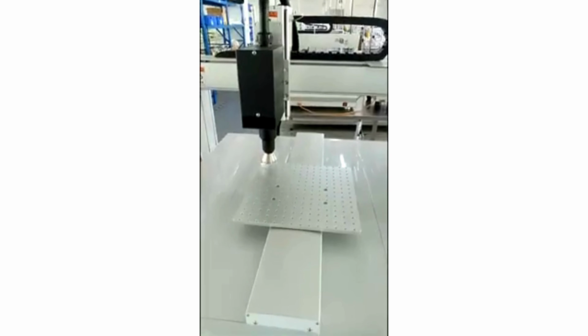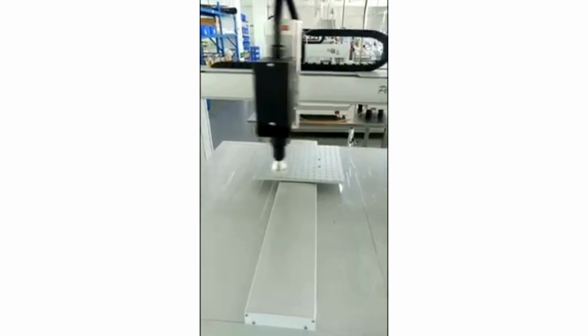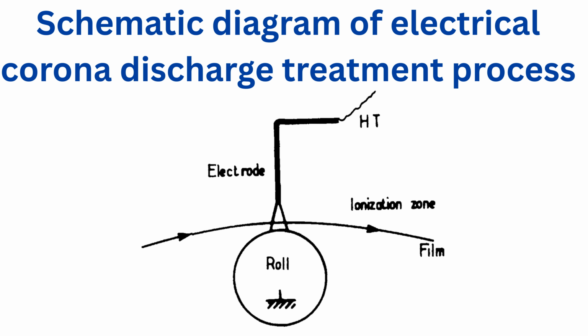The electrical field generated excites the gas molecules, that is, air, and dissociates some of them. The charged active species may react with polymer molecules, which are activated accordingly. Machine configurations vary with the electrode geometries, the electrical characteristics, and the film speed. One of the important parameters is the electrode film surface distance, which should not usually exceed 2 or 3 millimeters. Most frequently, 20 kilovolts electrical currents are applied, with frequencies ranging from 10 to 20 kilohertz.